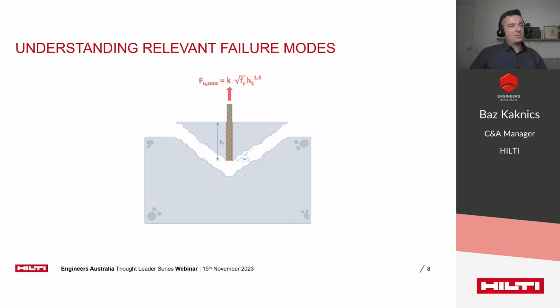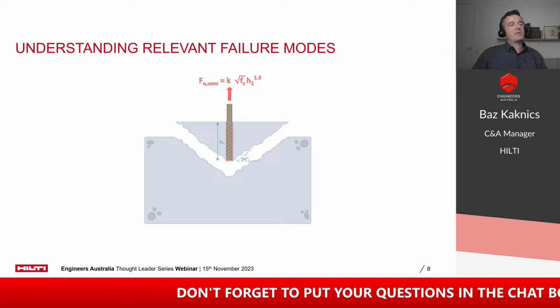Note that the cone capacity is directly proportional to the concrete's tensile strength, which here is expressed as the square root of the compression strength. And more importantly, there is an exponential function relative to the embedment depth, which means that selecting a deeper anchorage length will result in a significantly improved cone capacity.